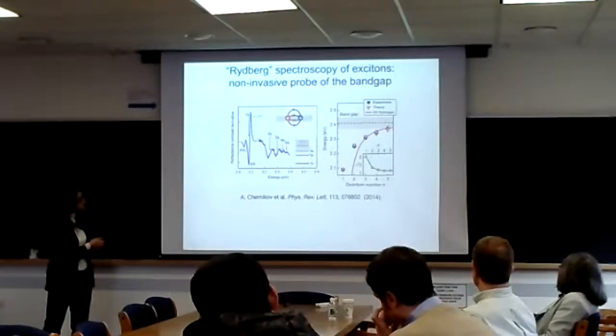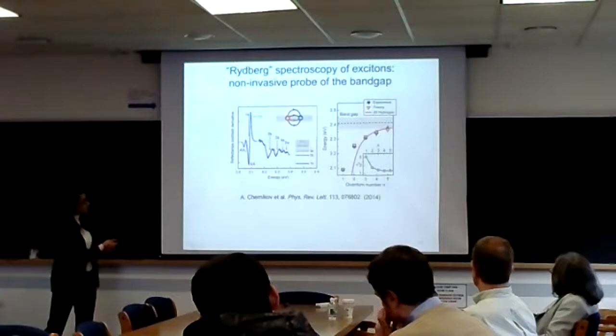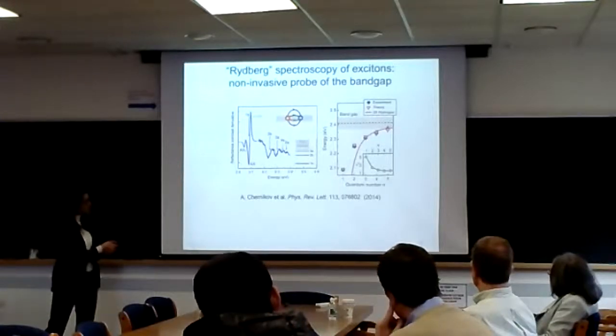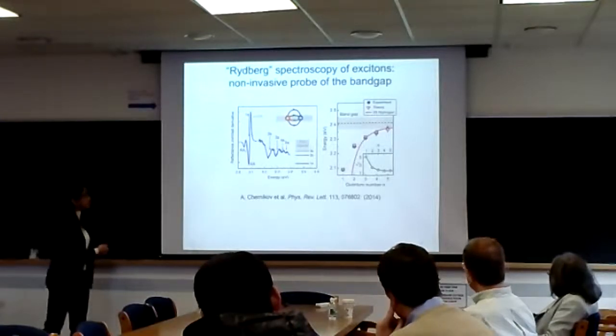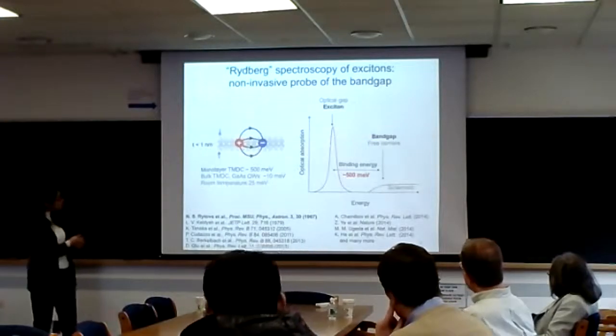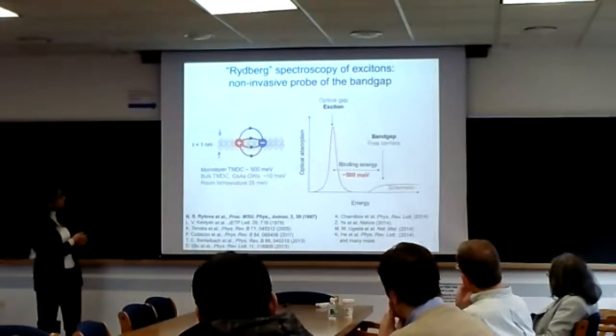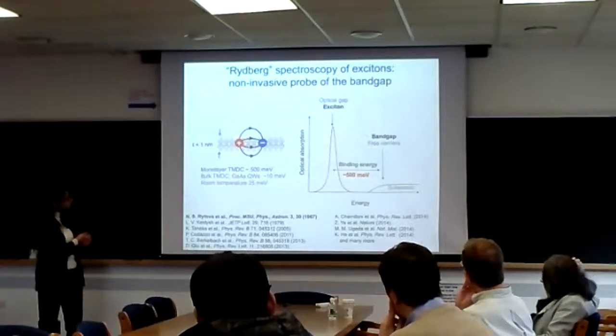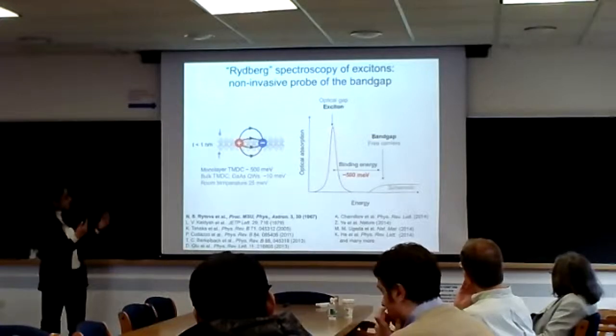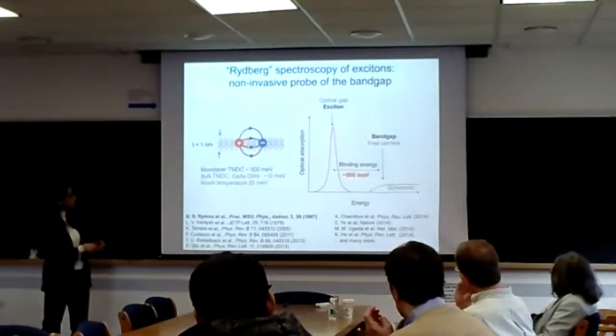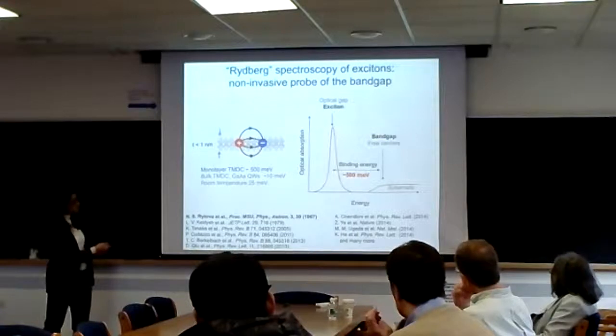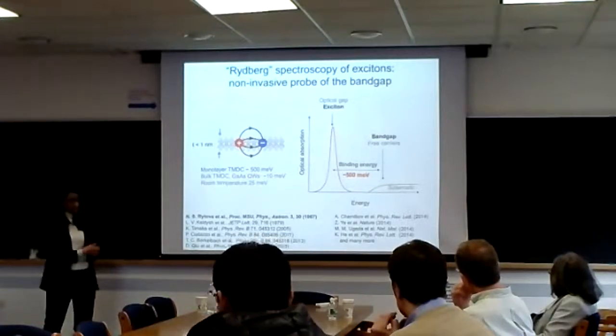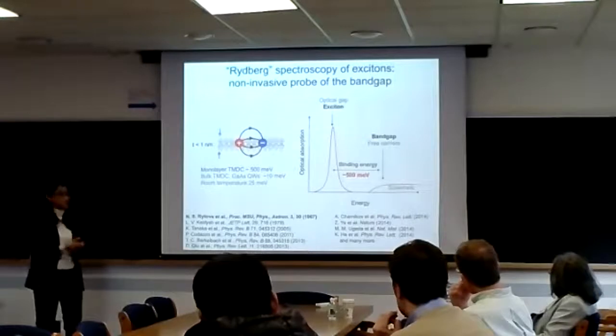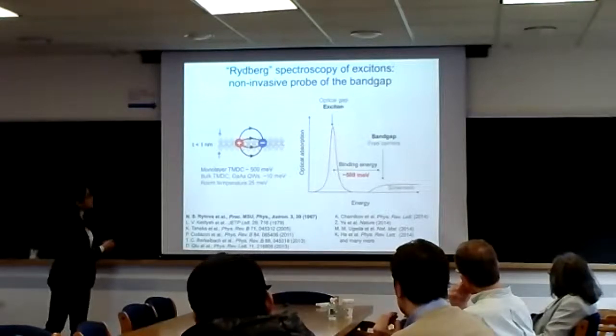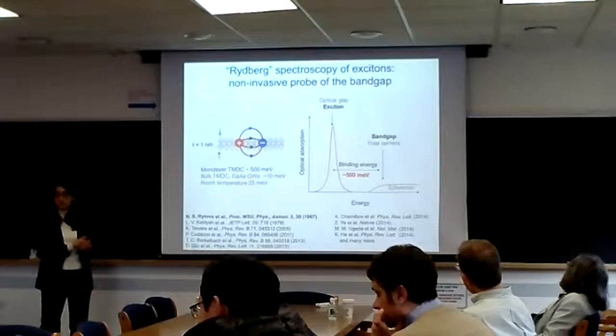An important thing to note here is that this is a consequence of non-local screening. Your ground state sees quite a bit of the material, and as you go to the excited states toward the quasi-particle gap, they're sensing mostly only the environment. So to summarize, here you have your exciton sitting in your 2D system, and as you change the Bohr radius or the distance between these carriers, you have a series that's highly non-hydrogenic, and you end up with a system that has a binding energy of about 500 meV compared to bulk semiconductors, which were on the order of 10 meV.